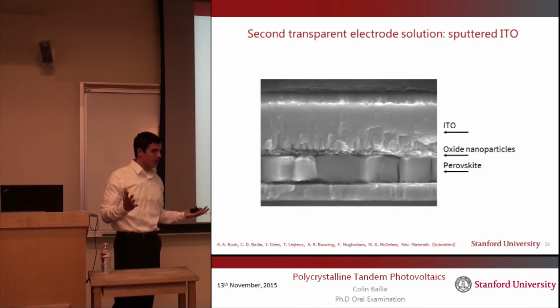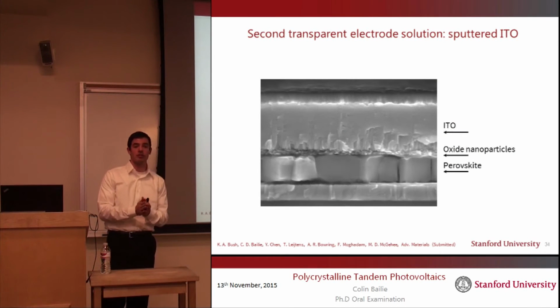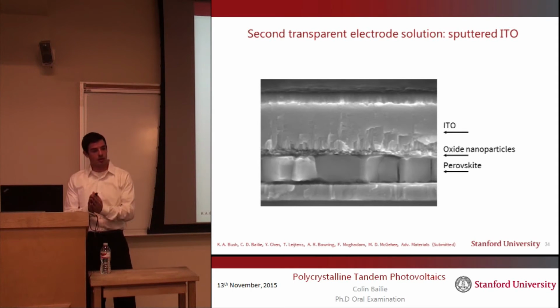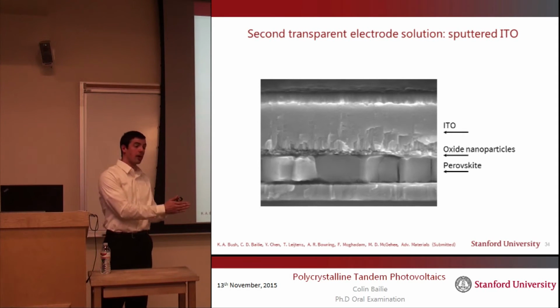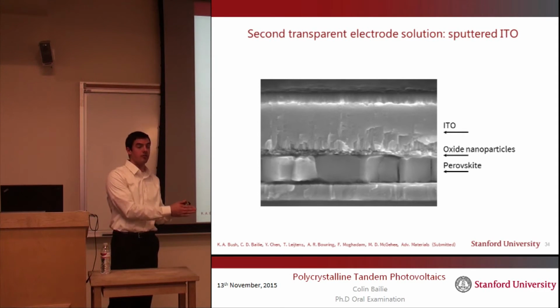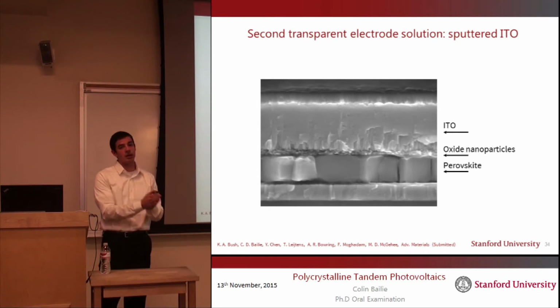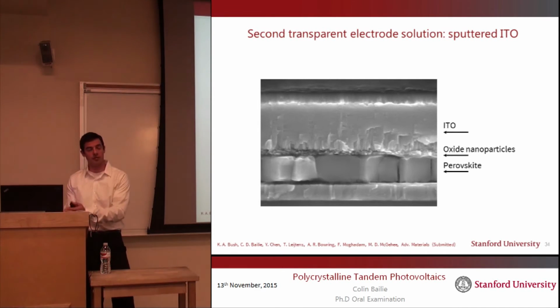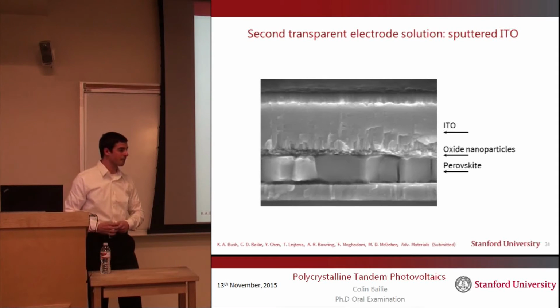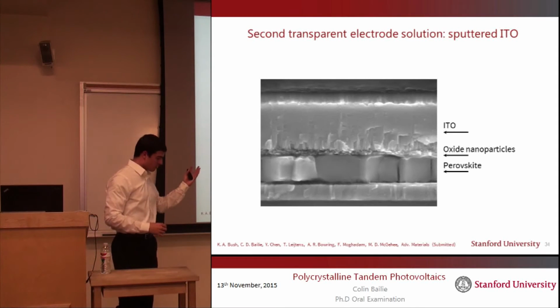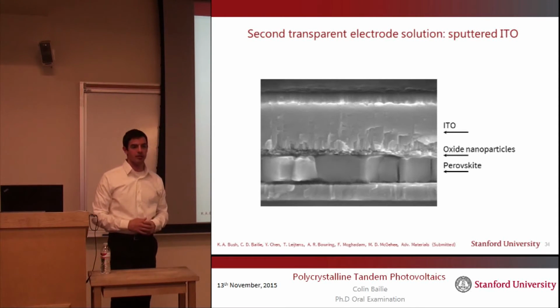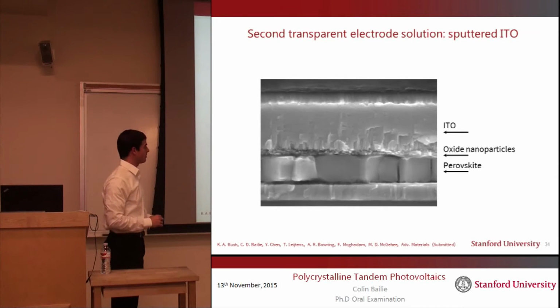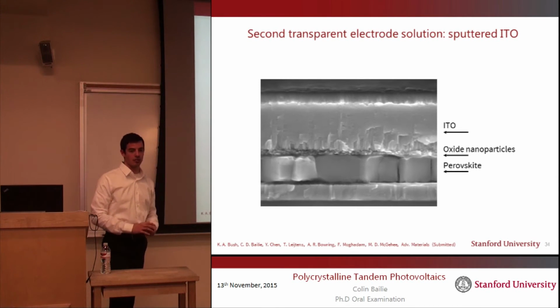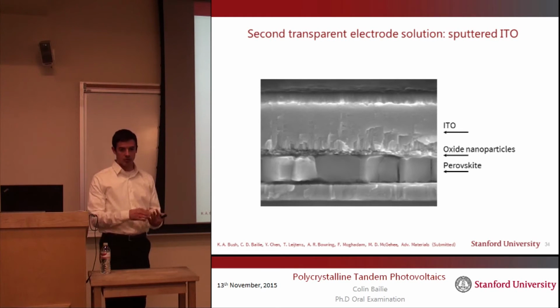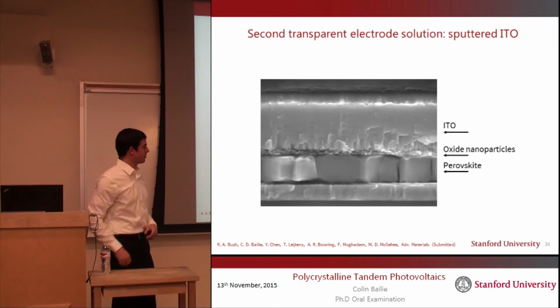So we needed now a transparent electrode solution that both was compatible with the deposition requirements of the perovskite, as well as stabilized the final solar cell that you make. And the transparent electrode we came up with didn't require a whole lot of imagination. ITO is the standard industry transparent electrode, and it's ubiquitous. It's in all of your touchscreen devices.